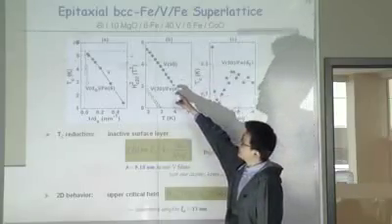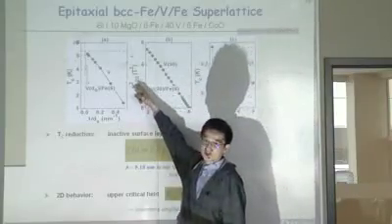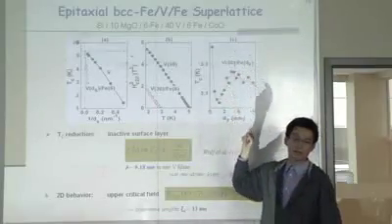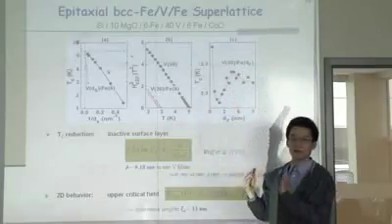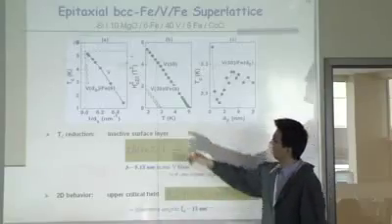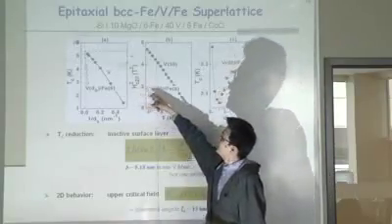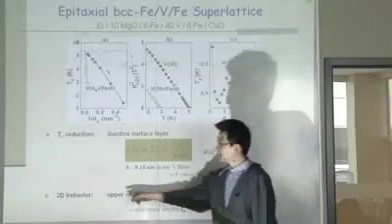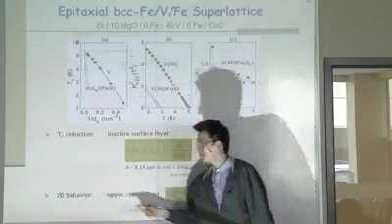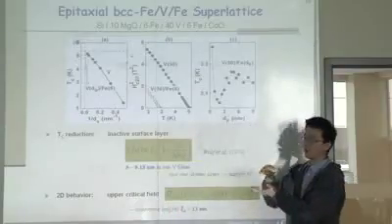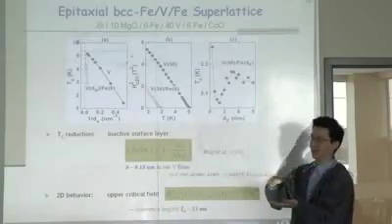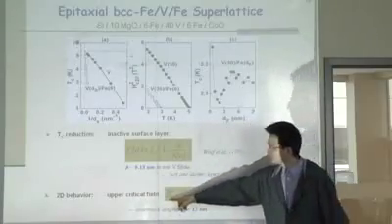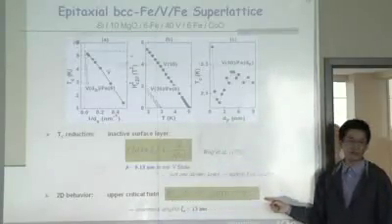The second piece of information shows you the critical field. We call it the upper critical field because vanadium is a type 2 superconductor. It will have two critical fields. So this upper critical field squared clearly depends linearly on the temperature. This is already known in the literature because this is a two-dimensional behavior, and our vanadium film is a film, so it behaves two-dimensionally. So the critical field should follow this equation.